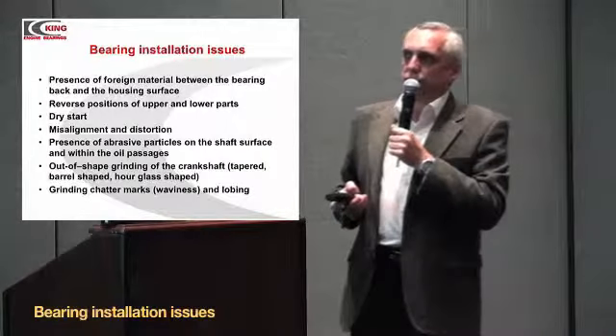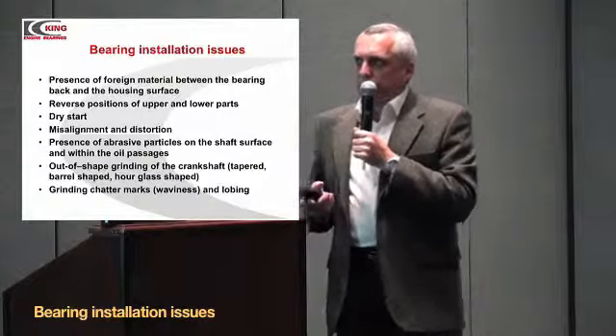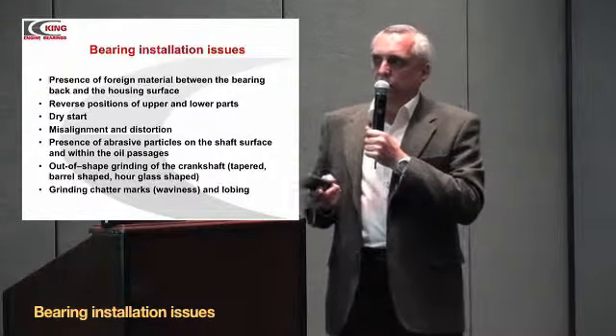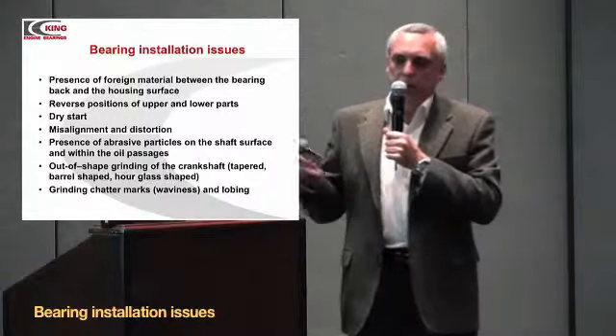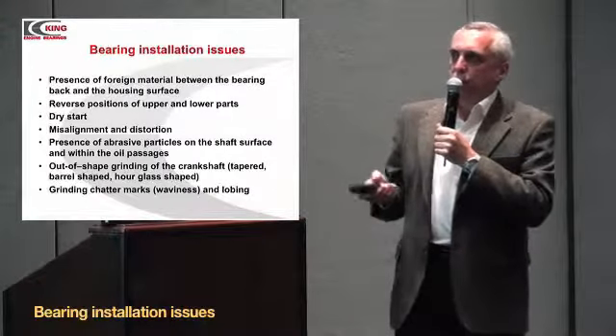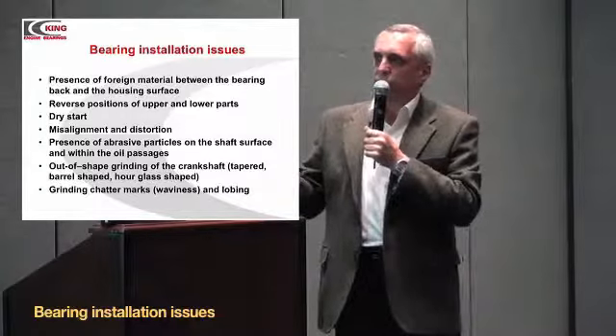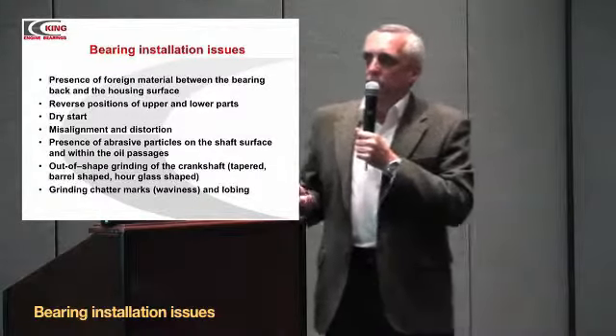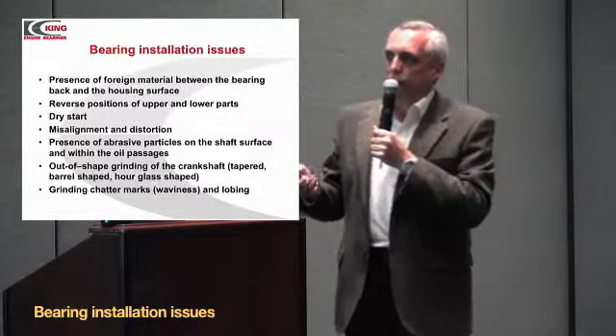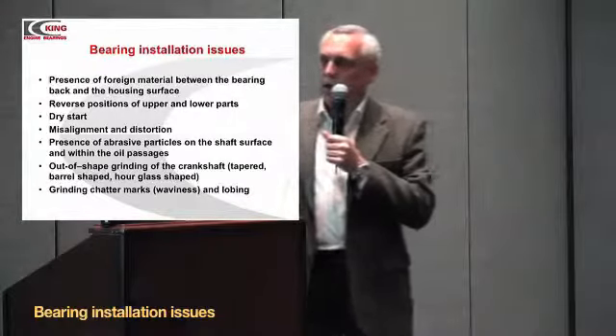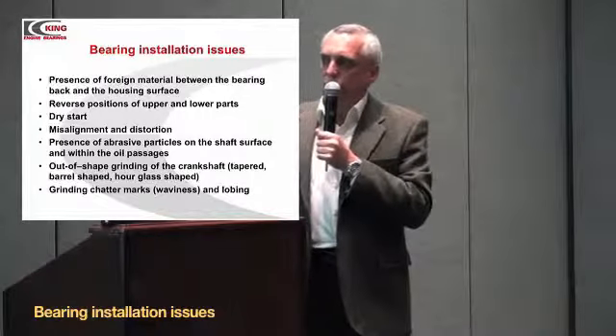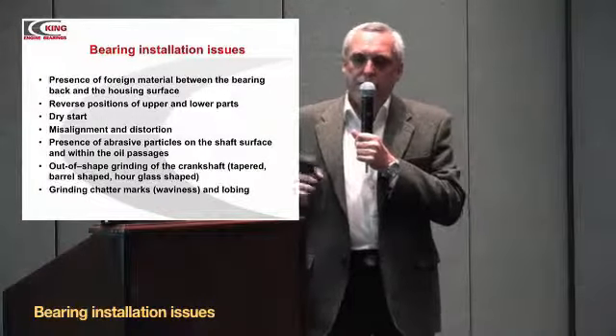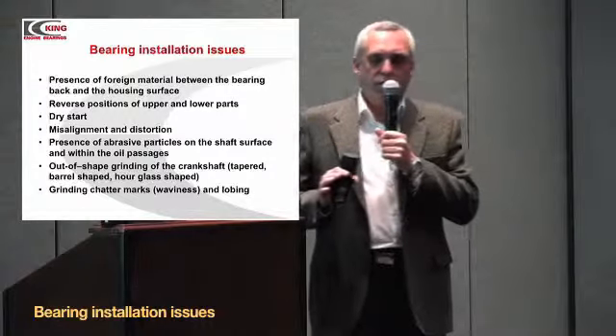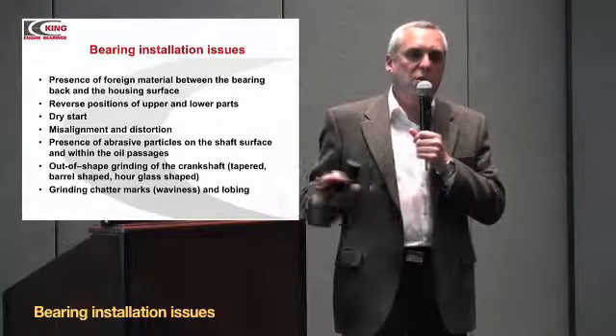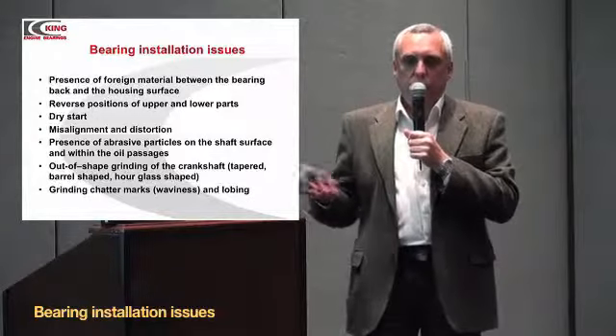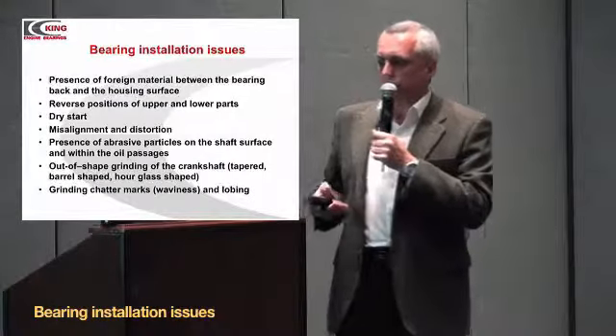Misalignments and distortions. Presence of abrasive particles on the shaft surface or within the oil passages, the abrasive particles after grinding. Out of shape grinding of the crankshaft: taper, barrel-shaped, hourglass. And other grinding defects like chatter marks, waviness on the shafts. I know this defect is not always visible, but it breaks completely the hydrodynamic regime of bearing, and bearing doesn't work at all if there are some waves on the journal surface.